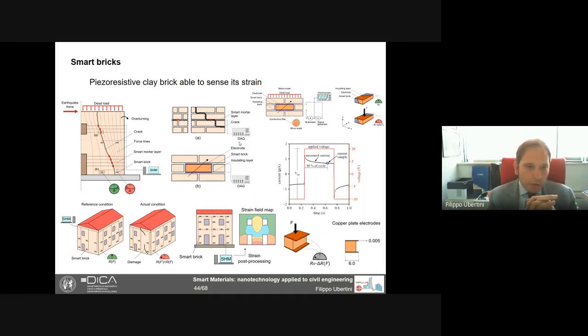But what we want to do is take measurements from smart bricks periodically, and if there is an earthquake, we compare the post-earthquake with the pre-earthquake conditions. And of course, we can do this automatically. And what we expect is that if there is an earthquake, then there are cracks forming in the structure, which means that the loads change their ways from the top to the foundations. So it means that under dead loads, we will have changes in permanent strain within different portions of the structure.